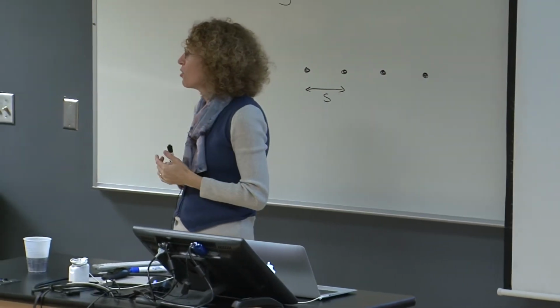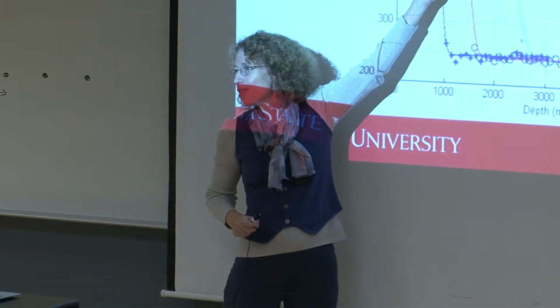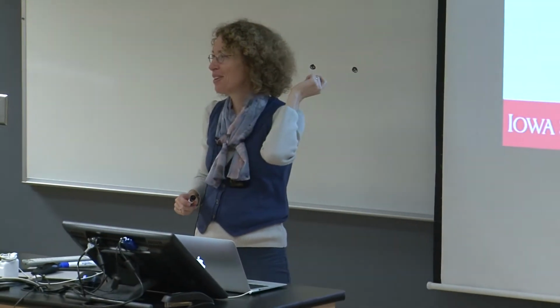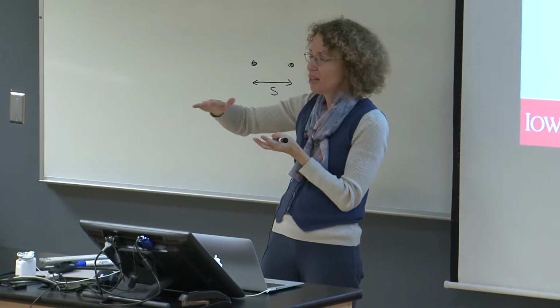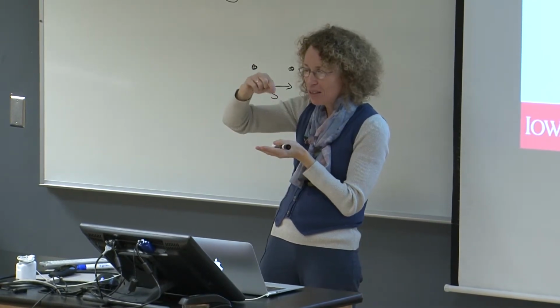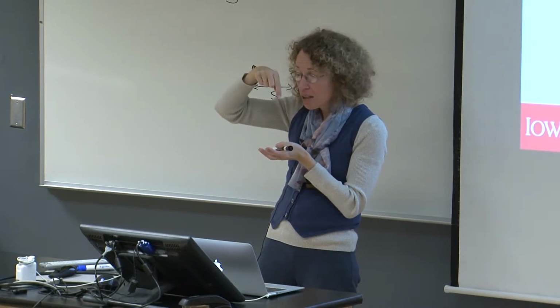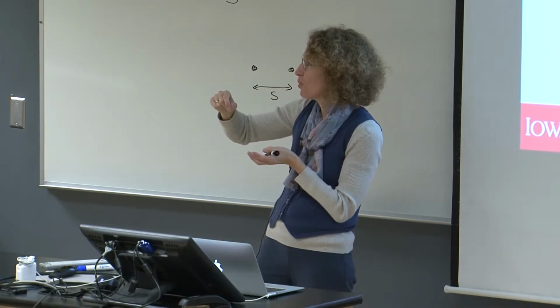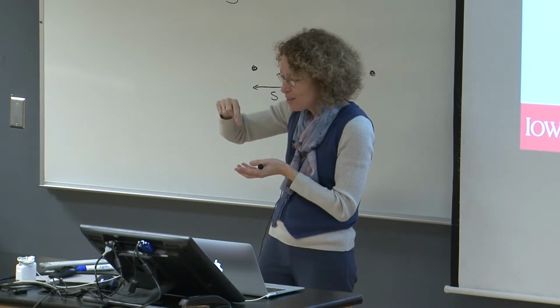But we sort of lack a good non-destructive way of measuring this. Does anybody know how these were measured? Do you have any experience with hardness measuring? Okay, these particular ones, you have to slice your rod and you polish it, and then you take a little tiny indenter and you measure the size of the dent that you can make with your indenter. Okay, so the bigger the dent you can make, then the less hard it is, and you have to do all those correlations. So it's a long and tedious process. So we want to replace that with a simple non-destructive measurement.